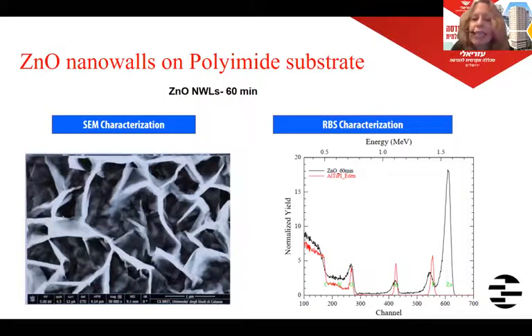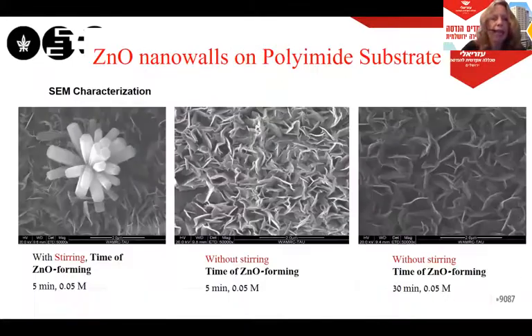And you can see the spectra of ZnO grown on aluminum titanium polyimide. The black line is the ZnO structure, and the red one is just the polyimide. And we tried different conditions. We did ZnO on both, this is just a polyimide. We did it both using stirring and without stirring.